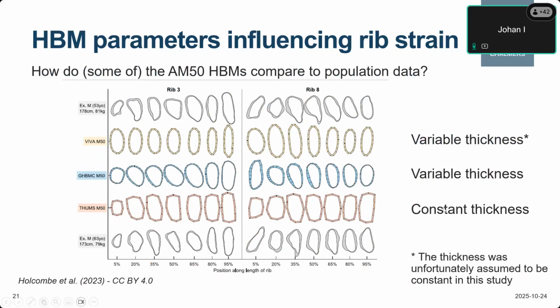We could notice that, in this case, the THUMS model uses a constant thickness of the cortical bone. The GHBMC uses variable thickness, and actually the VIVA Plus also uses variable thickness, but there was an error in this manuscript or this paper. There is an error in this paper, so Sven calculated this as a constant thickness. So basically the curves that I will show on the following pages are not valid for the VIVA Plus model.